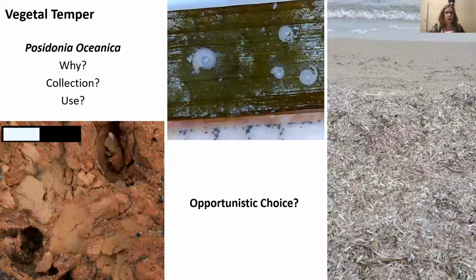I have to say that in Malia, only Posidonia oceanica has been identified, and the numerous salt efflorescences recorded in the geoarchaeological sample that I usually show on top of the seagrass impression indicates that these plants were not washed in fresh water before they were incorporated in the matrix, in the mixing. And this is actually also confirmed by the numerous small marine gastropods that were found within the bricks. In this case, I wanted to show you a seagrass that I collected a couple of years ago, with all the small gastropods still attached. So this is how the seagrasses were collected from the shore and then added to the soil mix and to water to create the mixture to produce the mud bricks.